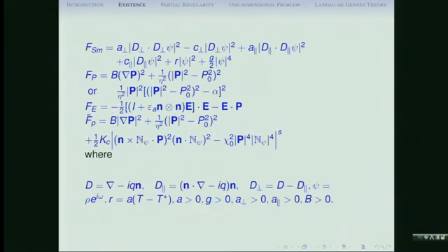Okay, here is the schematic energy. You have seen this one last week. Then we're talking about this schematic energy functional, and then you have the energy functional associated with the polarization vectors. There are many different kinds of polarization terms. This is the simplest one. You can either consider the saturation case, where the magnitude of P is constant, or you can put a P squared and the fourth order term.